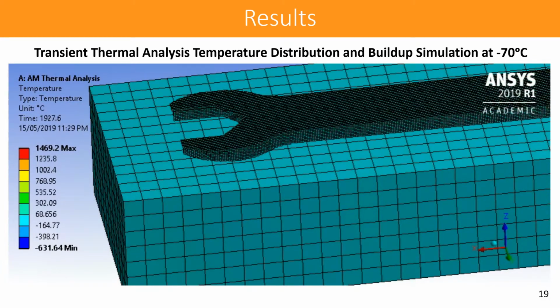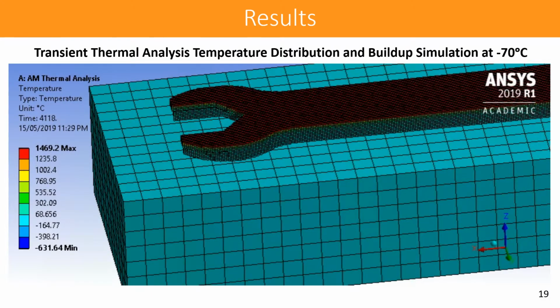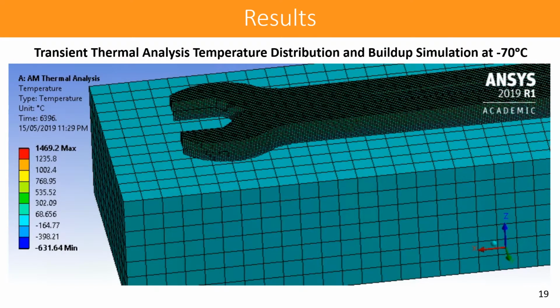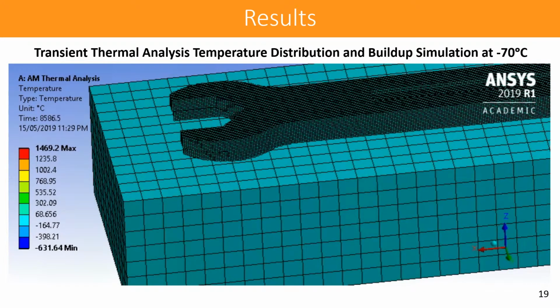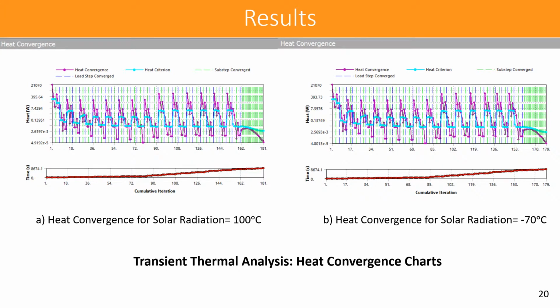This is showing the transient thermal analysis of study 2 at -70 degrees Celsius. The heat convergence charts for transient thermal analysis are almost similar, given the similar temperature distribution, but the lower radiation converges ahead of that for the higher radiation temperature. The graph is divided into two parts. On the left side, the build, and on the right, with a faster convergence rate, the cool down iterations, approximately from the 162nd iteration onward.